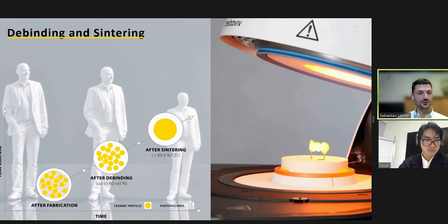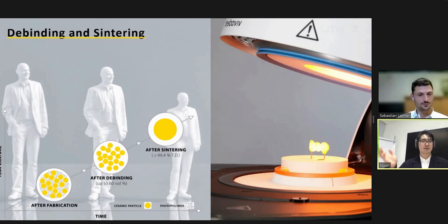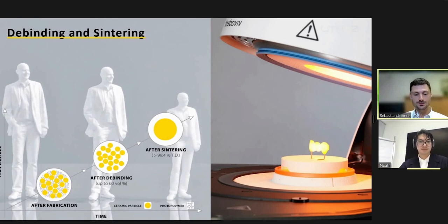But we have a very, very low density in here, and so we have the last step, the sintering. In this step, the sintering and crystallization in the lithium disilicate takes place, and we create the dense and strong part. Very cool. So in a normal 3D printing process you would do a typical alcohol wash, and here you're just doing the debinding, which is essentially just using heat. Yeah, and then you go to sinter. That's true. For sure, we have a cleaning step in between where we have our own developed solvents to make this cleaning as easy as possible. Then this debinding helps us to get rid of all the polymer inside the part. So we burn out, and after the sintering process, we have basically the full ceramic. We have no composite anymore. So this is the lithium disilicate after this step, as you know from pressing or milling.